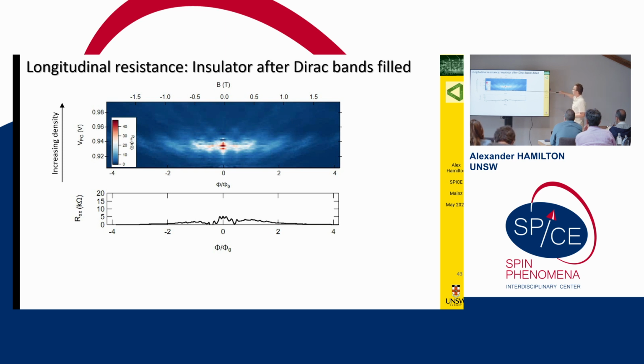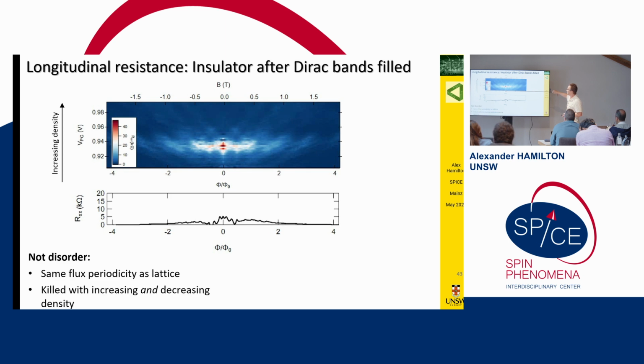So this is now, we go to the strongest possible modulation, and I'm going to sweep the chemical potential and just look at the resistance. And at some point, there's a huge peak in the resistance, and then it drops away again. Even at that resistance point, I've got the same flux periodicity as the lattice, which means that the electrons in the insulator know about the lattice that I put down. It's not a disordered insulator. The other thing is that this insulator is killed both at high electron densities, well, if it's a disordered insulator and you throw enough electrons in, you'll kill the insulator, but also at low electron densities. So that really argues against Anderson localization. It only happens exactly when we predict the flat band to occur.